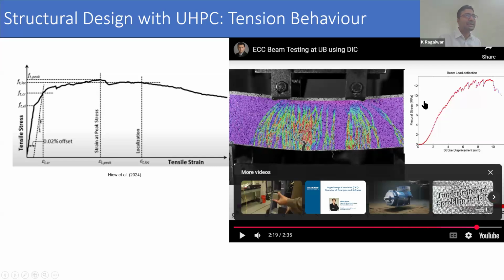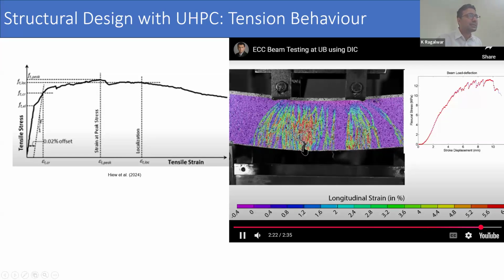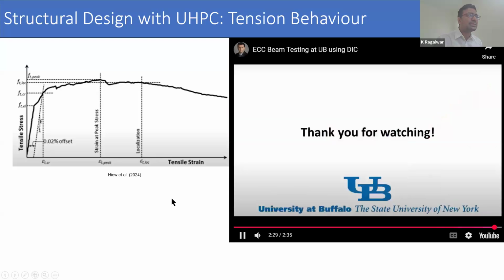And therefore, we can see that pseudo strain hardening behavior translates into deflection hardening as well. So what is deflection hardening? It is after the first crack appears in deflection, you see that the beam is able to take higher loads. Okay. And this is where the localization has started occurring. So you would see that this particular crack has completely opened up.